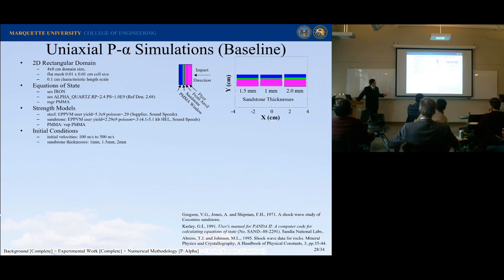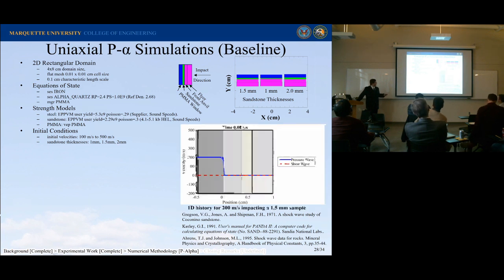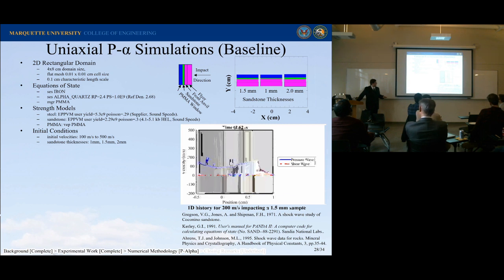For the sandstone, I used an EPPVM model that I got off of I think it was either Gregson or Ahrens and Johnson. And I went back from a Hugoniot elastic limit to find the yield strength. And that's valid because they did the test at high strain rate. So here's the initial conditions. We had an initial velocity of 100 meters a second. And you can see this wave come through the first material into this material, go through the sandstone, and then it hits the back wall, and that's where we collect our data.